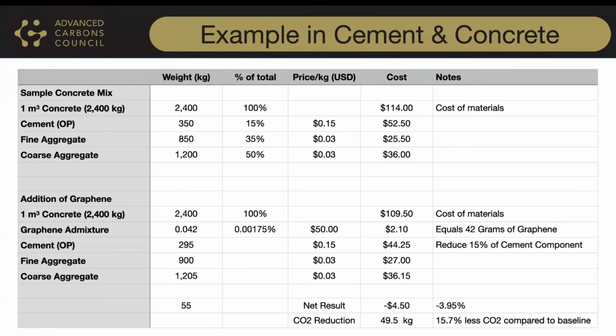Now, if we drop to the second half of this table and we look at the addition of graphene, we have the same cubic meter of concrete, but now we're going to add graphene at an extremely low load factor. So you've got 0.042 kilograms, or just 42 grams of graphene added to this mix. And with that graphene priced at $50 a kilo, we're adding $2.10 to the cost of goods. But because graphene enhances the strength quality, we're able to then reduce the cement component out of our concrete mix. We assume we can take 15% of the cement portion out of this concrete mix while retaining the same strength or better profile and also getting better cure times, which is typical.